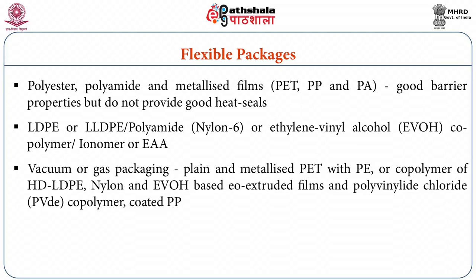To enhance the shelf life of products, either vacuum or gas packaging can be resorted to. Vacuum packaging is suitable for packing sweets having a rigid structure, while gas packaging is more suited for softer confections. For these applications, materials such as polyester, polyamide and metallised films possess very good barrier properties towards oxygen and aromas, but do not provide good sealability on their own. They are generally combined with polyethylene and its modifications to provide sealability and inertness. Hence the combination of polyesters and polyethylene is most suitable for flexible packages for confectionary items.